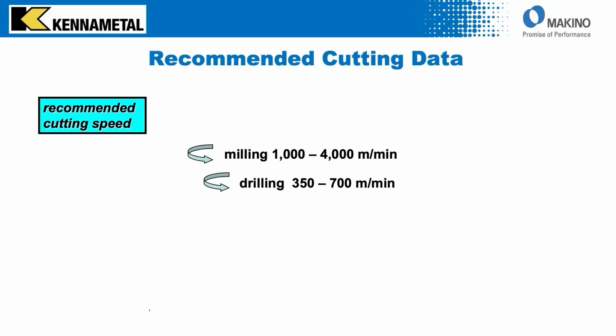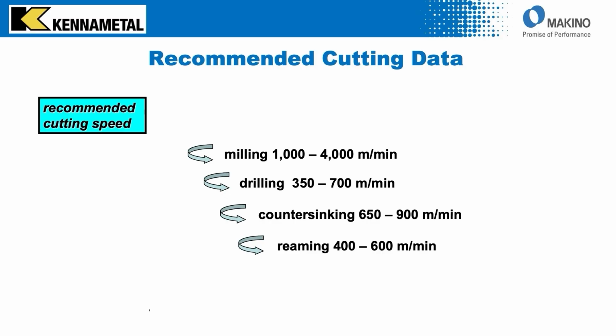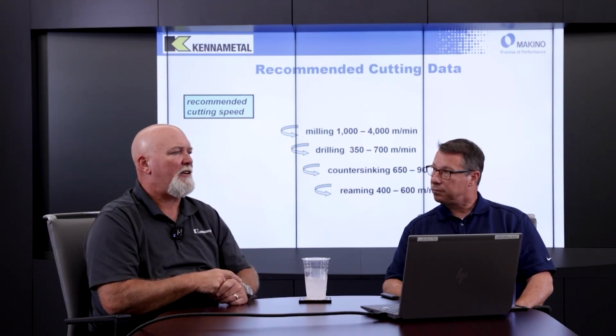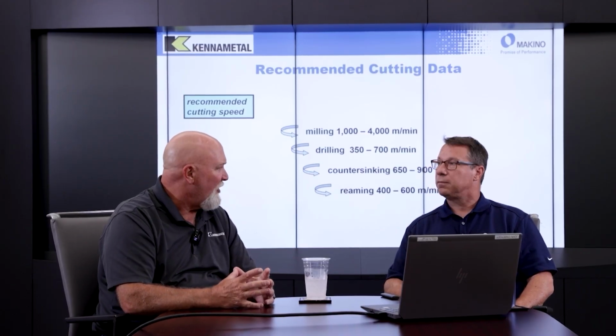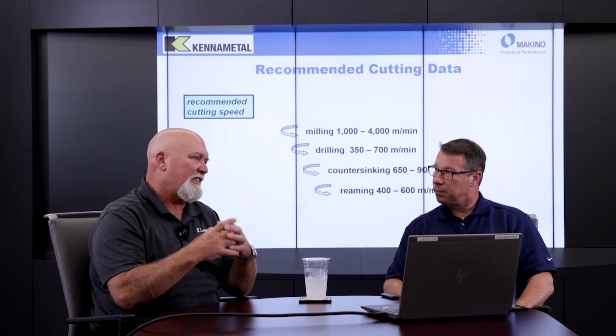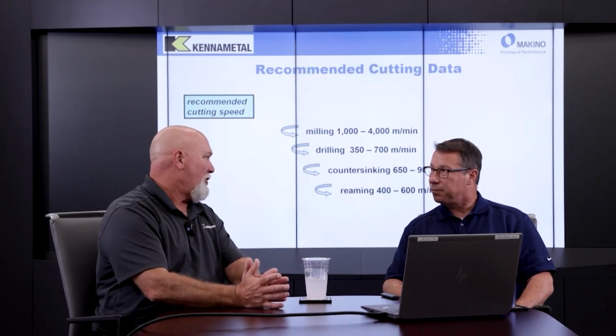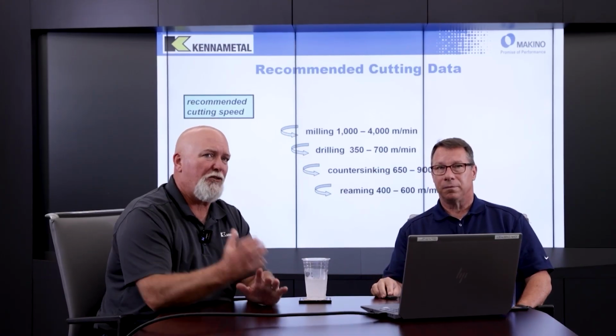For drilling, we're in the 350 to 700 meter range. Countersinking, very similar. We do a lot of tools that are drilling and countersinking or reaming and countersinking. So they're all in a similar range. And the reason that they don't run at the higher speeds that we see in milling is because in all those instances, whether we're drilling, countersinking, or reaming, those tools all have radial margins on the diameters. And because we're basically burnishing that hole down, we can't run at the elevated levels, or we'll actually burn the part up going in. But those are the ranges that we run in.